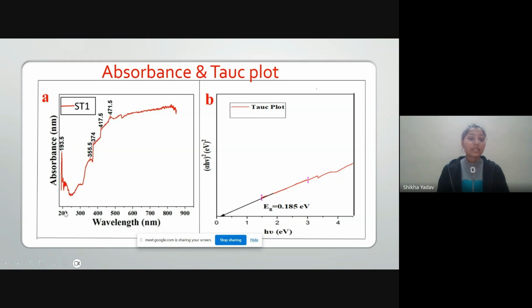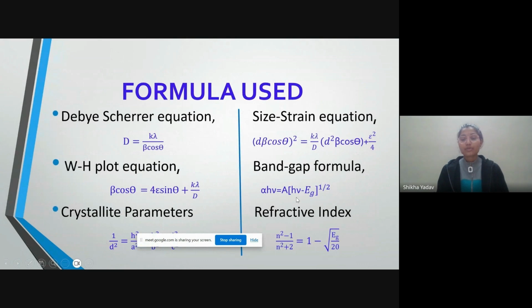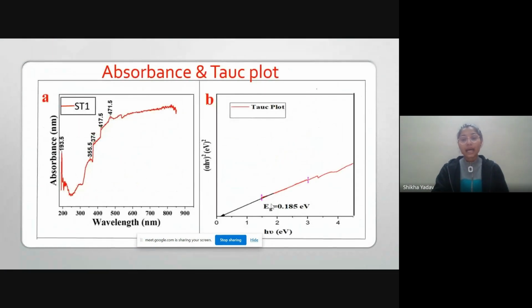Firstly, let's see the absorption plot. In this absorption plot, we can see that the maximum absorption is seen in the visible region. These are some broad peaks that are seen here. Using the Tauc plot method, we calculated the band gap. This was the equation that I used to calculate the band gap, and the value that I obtained was 0.185 electron volt.